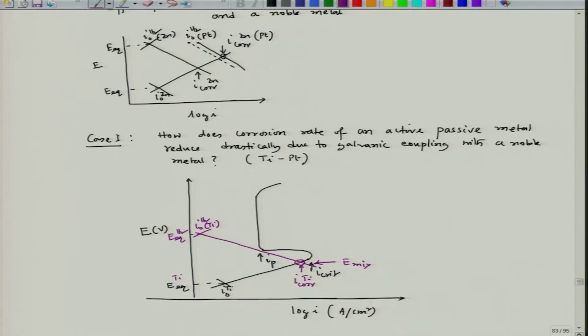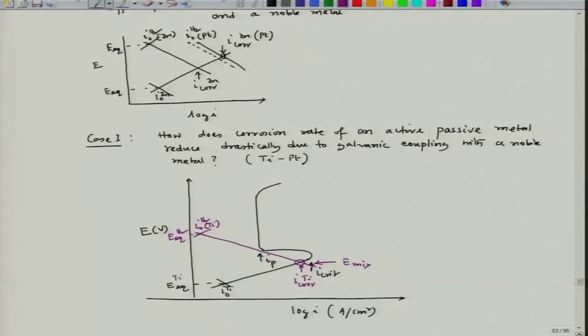Now, if we have platinum on the titanium surface, then the platinum will provide surface for hydrogen evolution reaction, and its exchange current density on platinum surface will come into picture. The hydrogen evolution reaction exchange current density on titanium surface is lower than that on platinum surface, but the equilibrium potential will not vary, because this is decided by the pH of the solution, considering the hydrogen gas is at atmospheric pressure, 1 atmosphere.